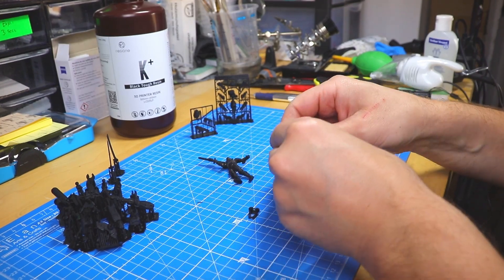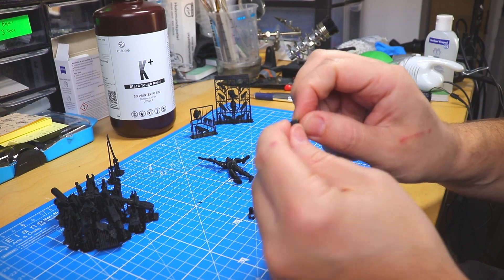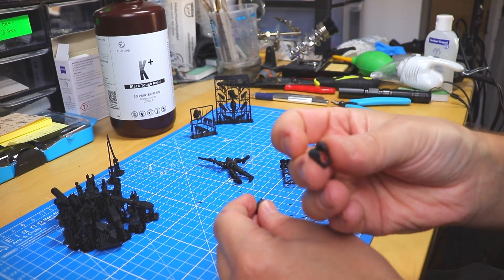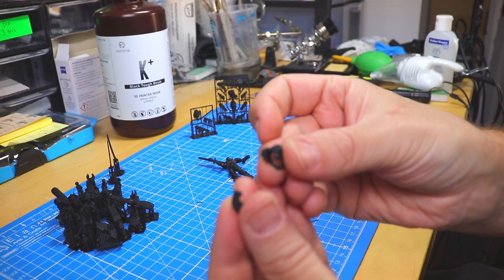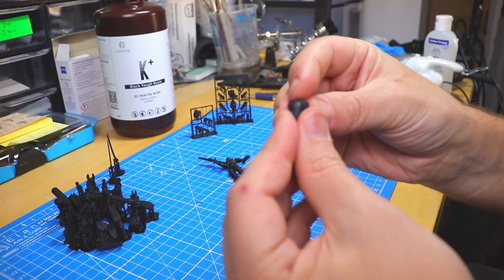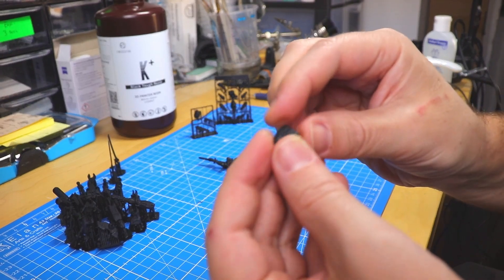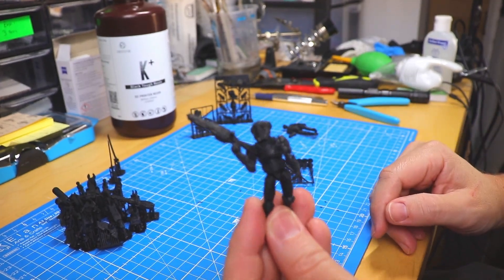What's really interesting is always this helmet part — that's why I like to use this figure for my resin tests, because this is a very, very small hinge. The resins I use usually require some flexibility and toughness at the same time, but they can't be too flexible, otherwise this joint will wear out quickly and the visor will just pop off with no effort. Nice little click — oh yeah, this is really nice! The helmet works perfectly with the three-second layer exposure. This is awesome.